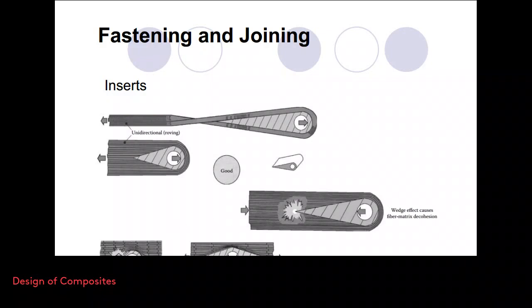What else? You can use such a metal ring. Remember that such a circular hole will generate a complex state of stress, and therefore the stress in this region can exceed the rupture stress and certainly may fail. So this is not a good design. So you can use such an insert for the alternating load, but in fact this is not a good idea because you may generate a debonding.